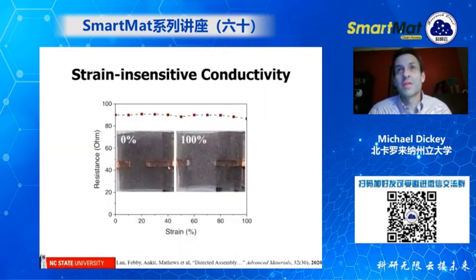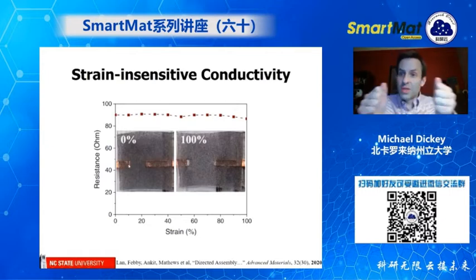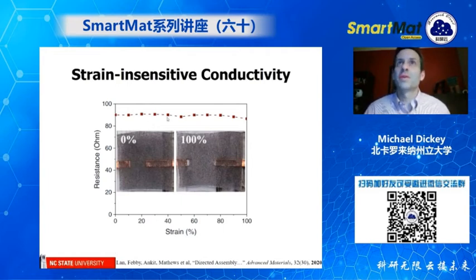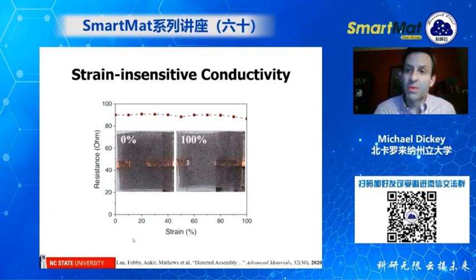One of the other cool things about these particles is that if you measure the resistance between these two copper electrodes and you start stretching it, remember, normally the resistance should go up, but here the resistance stays very constant. And we think that this is due to the serpentine shape that these liquid metal structures form. Okay, I have one last thing I want to talk to you about, and it's going to be a bit of a transition, but I'm still talking about liquid metal.